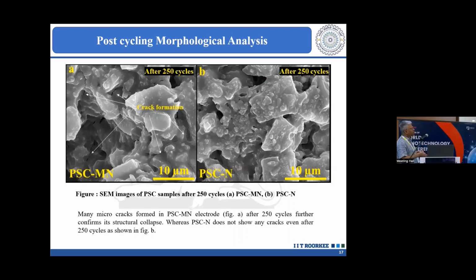So here after 200, 250 cycles, when we look at the morphology, we can find there are cracks formation, indicative of the crack formation, whereas this material does not show any evidence of the crack formation. So from the application point of view, or from the use point of view, it is very important to look at what morphological changes are happening with the number of cycles.